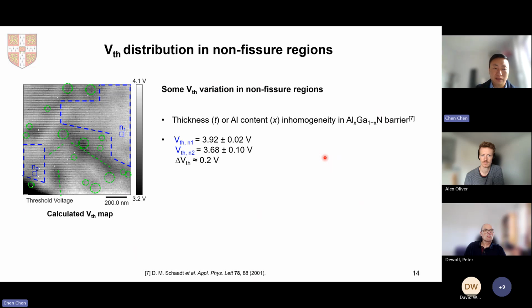For this quantitative threshold voltage map, another advantage is that based on the local threshold voltage difference, you can also quantitatively calculate how big the thickness inhomogeneity is, and also how big the aluminum content inhomogeneity is. In our case, for this sample, a 0.2 volt threshold voltage difference could be caused by a thickness inhomogeneity of about 0.8 nanometer, or aluminum content inhomogeneity of 0.05, or a combination of both.